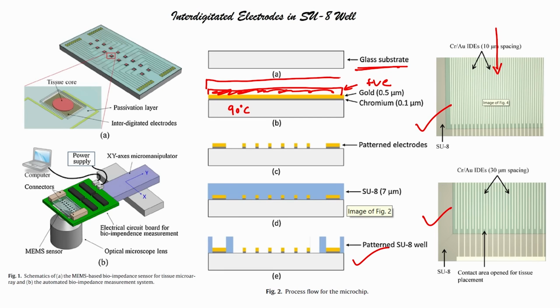Then when I attach the mask, the mask has some pattern which is similar to what you get here, right. After attaching the mask or loading the mask, I have exposed this wafer with UV light, then I have developed it, and then I have post baked it. After developing and post baking, what will I get? I will get a photoresist just on this area, right. Then I will etch this wafer, that is, etch chrome gold.